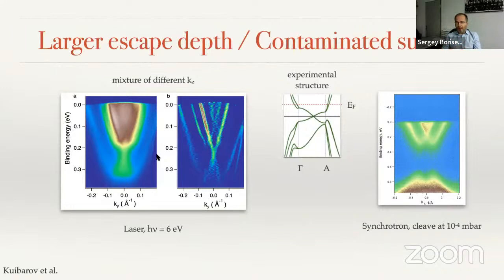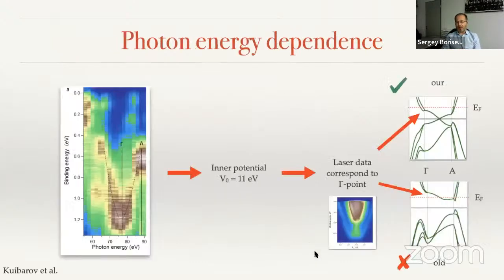And again, we see two sets of the features, which is in very good agreement with our picture and contradicts the picture that this is just a surface state. We tried to cleave the sample at 10 to the power minus 4 millibar, and we still saw the states as independent of the quality of the surface. So the argument here is that according to the universal curve, you're very sensitive to the bulk using this laser radiation. And you still see the two features very clearly, which speaks in favor that this is not a surface state, that this is a bulk state.